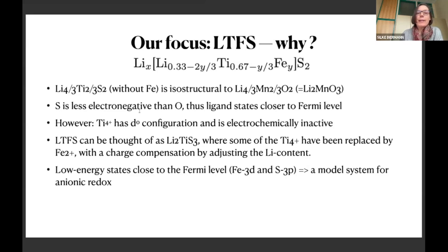Sulfur is less electronegative, so the ligand states move closer to the Fermi level, and that means the anionic redox process should become easier. However, in the pure compound here, the Li_2TiS_3, titanium is in the 4+ configuration, and the whole thing is actually electrochemically inactive.